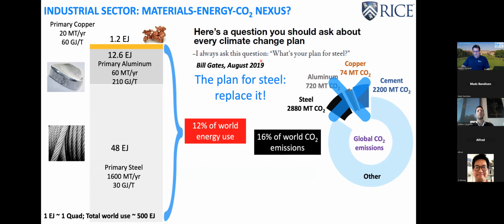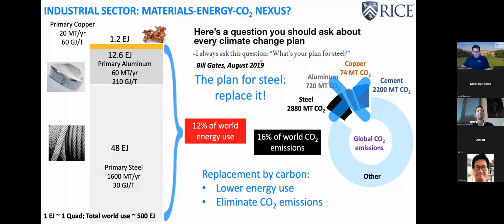So we're not going to do steel in a better way. We're just going to get rid of steel and replace it with carbon. And if we can do it with a lower energy use or comparable energy use, then we'll eliminate the CO2 emission because the carbon is going to be in the material. There's almost no carbon in steel, and there's no carbon in aluminum and copper and cement.